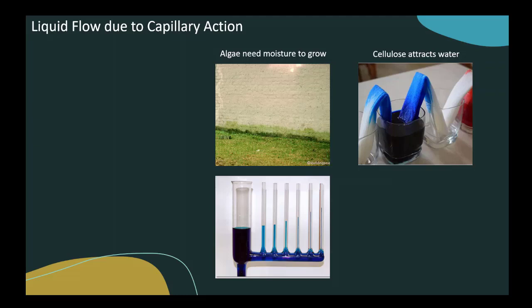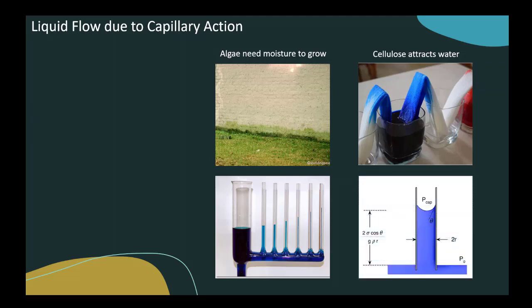If all the conditions, like the material type and the liquid type, are constant, but you change the diameter of the tube from left to right, the capillary height increases. The corresponding equation is here. It says that the height is 2 sigma cosine theta over g rho r. Sigma is the surface tension of the liquid, r is the radius, and g and rho are gravity and density of water. Two variables are here: theta, which is the contact angle, and r, the radius. So the capillary height is controlled by r and theta.